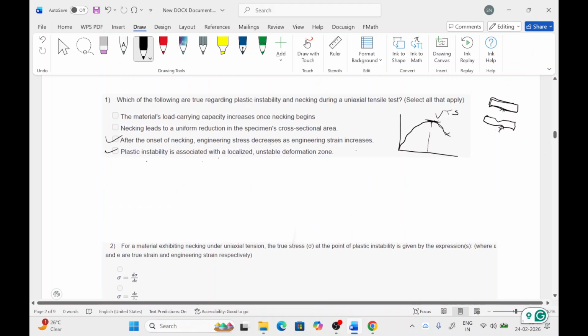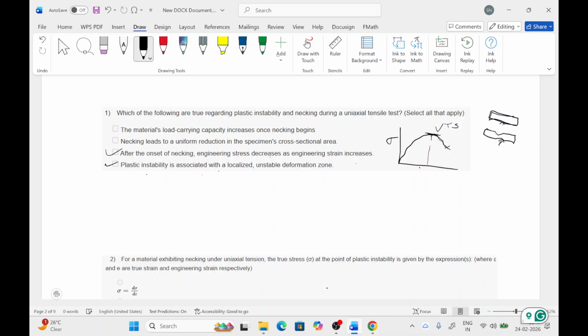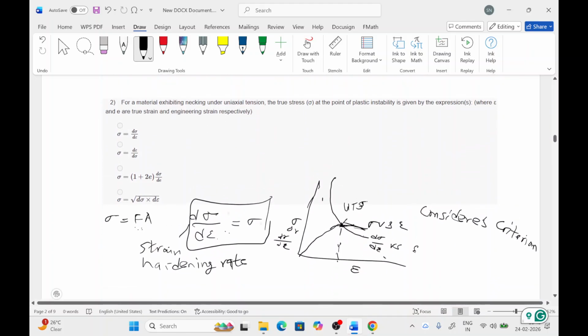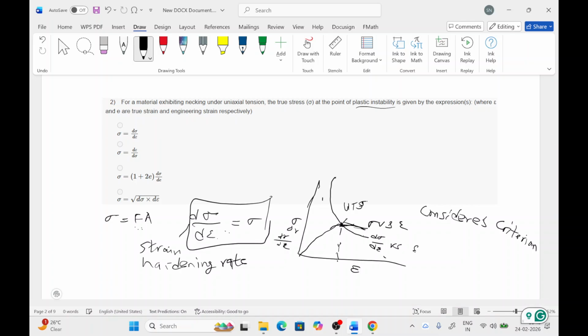So we got the true stress-strain uniaxial tensile behavior like this. After UTS the curve decreases, and up to UTS the material deforms uniformly, and after UTS the deformation is localized at some point. That localized deformation happens after the UTS. So only at UTS this behavior will follow, meaning the strain hardening rate will be equal to the stress value at UTS. So from this equation, the plastic instability is given by sigma equals d sigma by d epsilon.